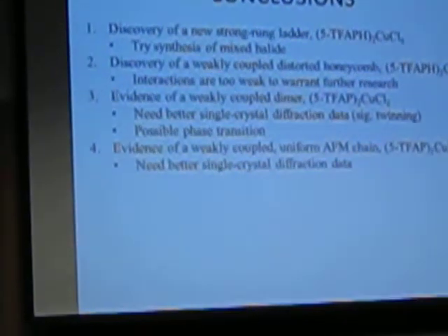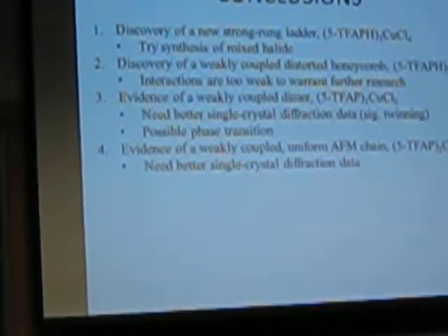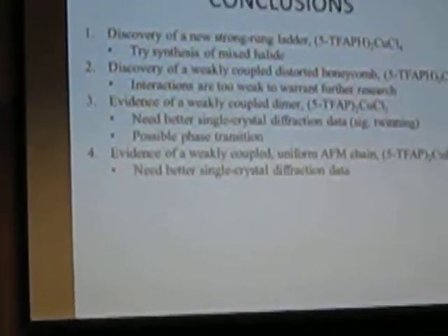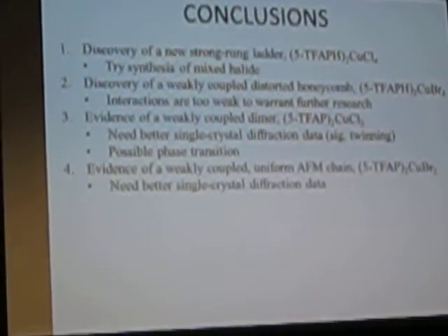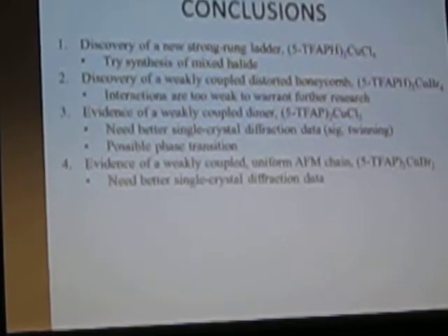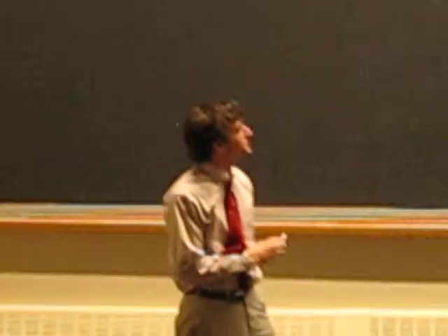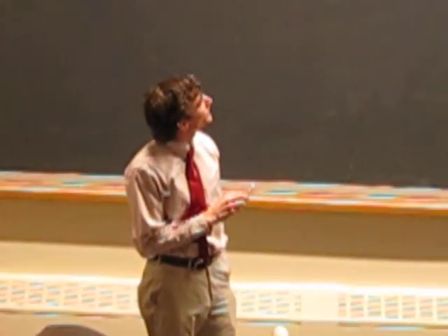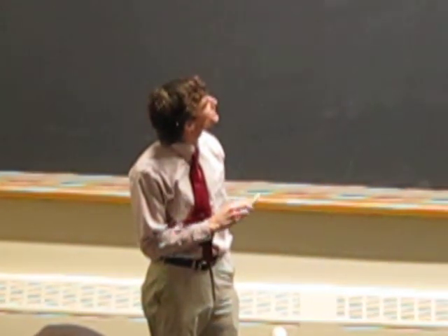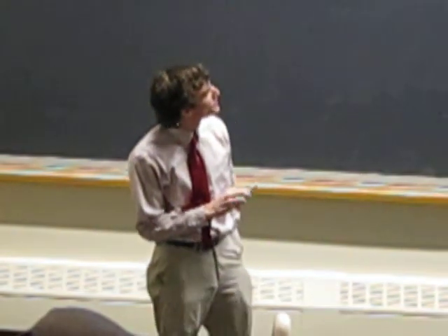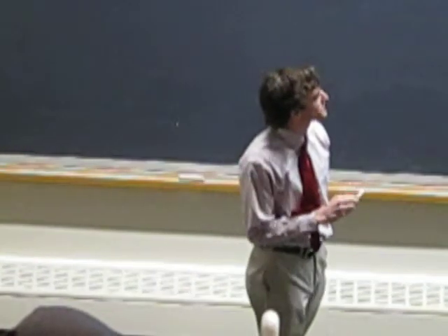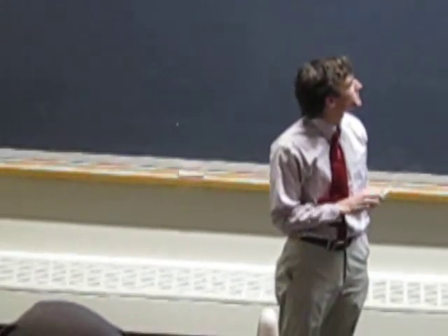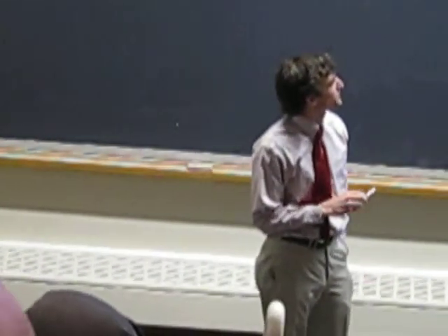And with that, we discovered serendipitously this distorted honeycomb structure. We were really excited that we were going to see some really exciting magnetism with this material, but it turns out that the exchange is just too weak to warrant any further study. So in terms of the neutral compounds, we just need better single crystal diffraction data, and to actually deduce what's going on in those materials.